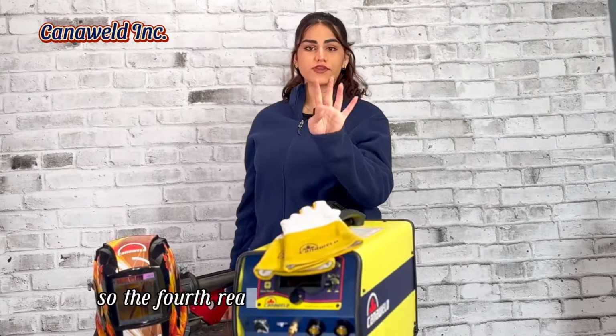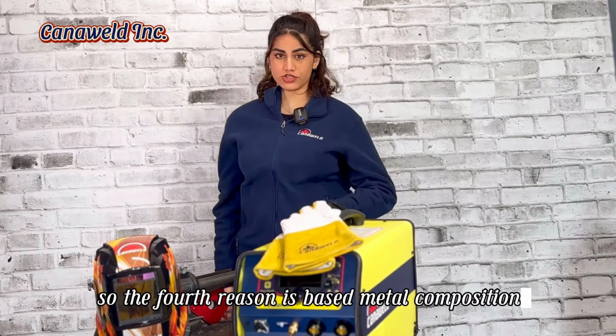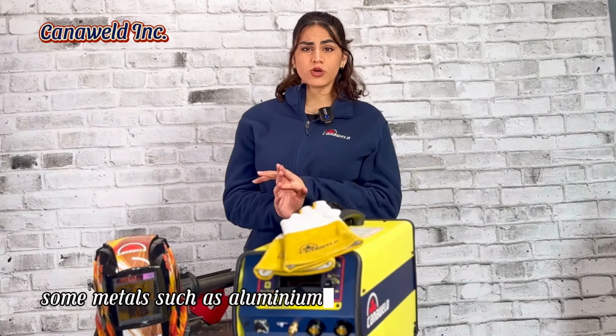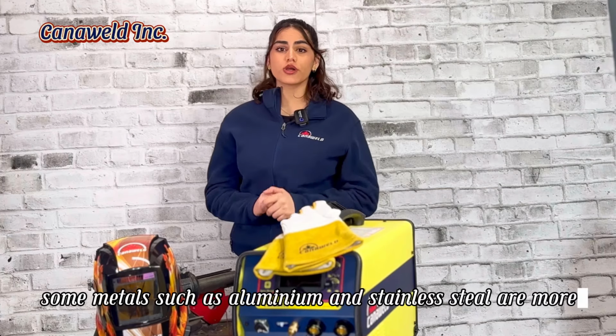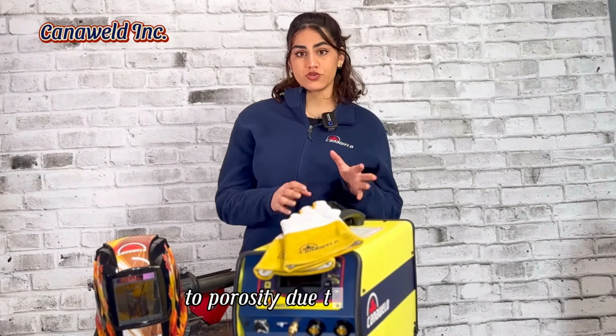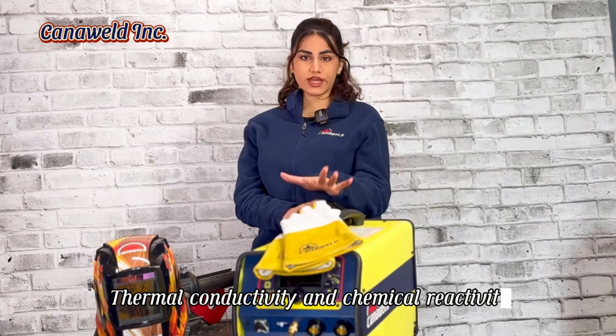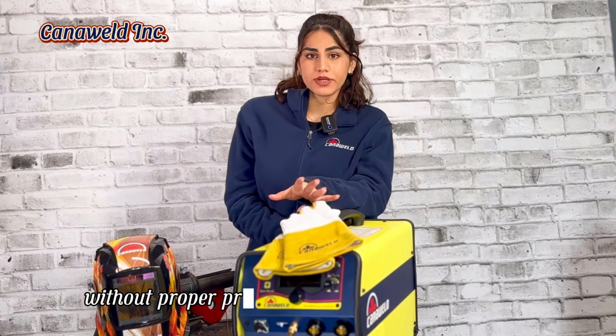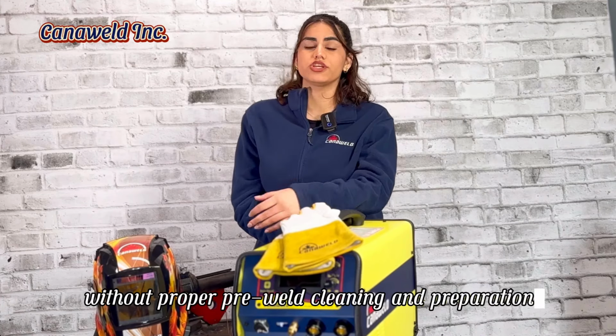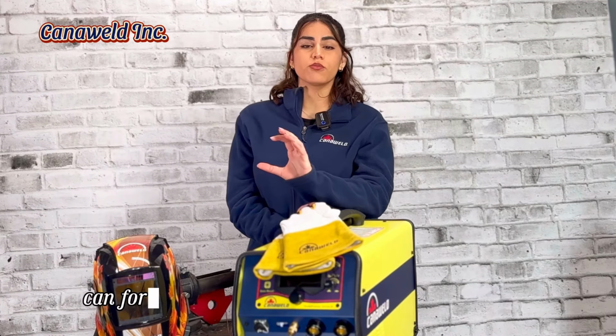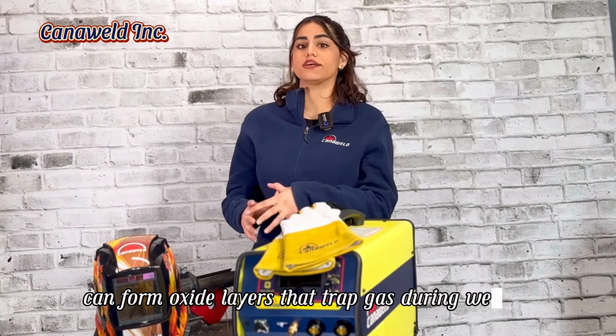So the fourth reason is base metal composition. Some metals such as aluminum and stainless steel are more prone to porosity due to their high thermal conductivity and chemical reactivity. Without proper pre-weld cleaning and preparation, these materials can form oxide layers that trap gas during welding.